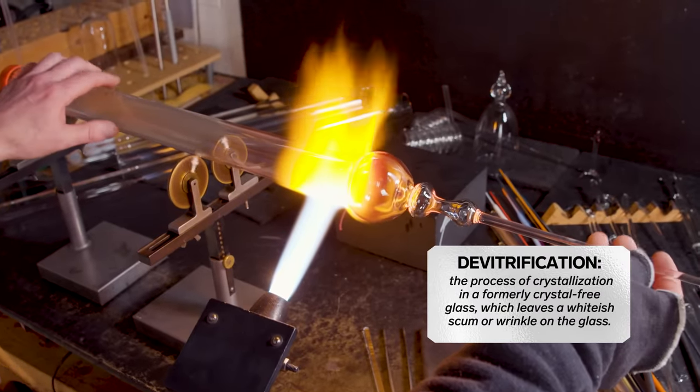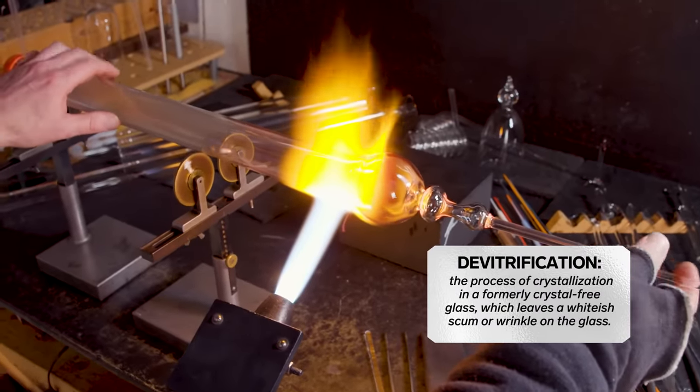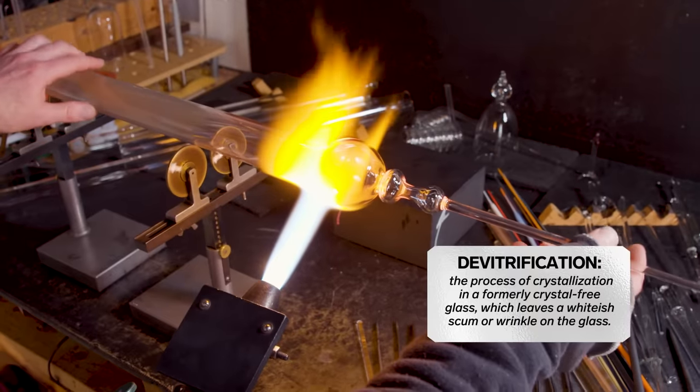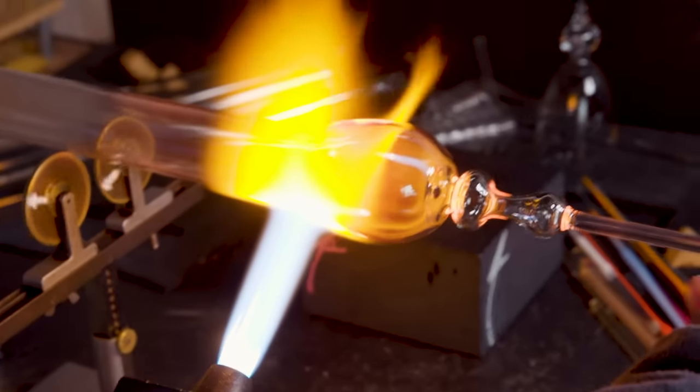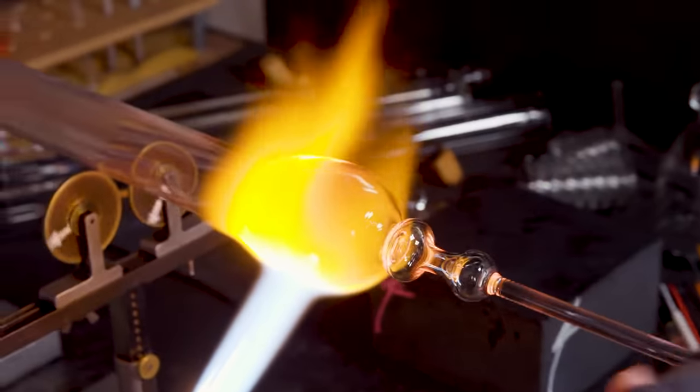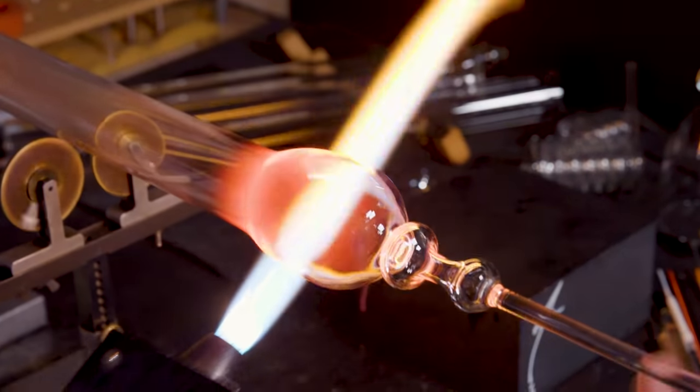Overworking the glass can cause de-vitrification because you burn all of the sodium out. So you want to try to work the glass as little as possible so that you maintain the integrity and the chemical properties in the glass that you need to keep it clear.